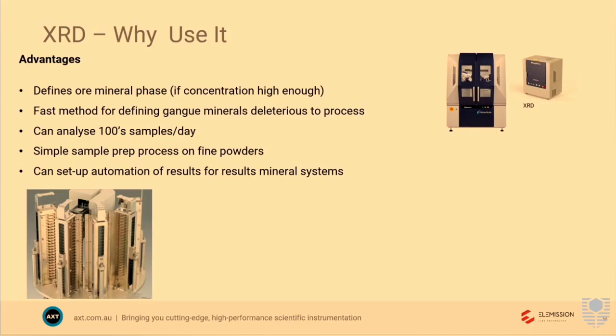All you have to do is pulverise, and then you actually have to micronise a little bit further to try and get everything down to hopefully less than 40 microns. The ideal particle size for XRD is meant to be 5 microns, but if you grind everything to 5 microns, you end up with so many amorphous phases that you can't analyse them. So industry typically will pulverise something down to less than 40 microns, and a researcher will be in shock horror, you've got to be less than 10, but industry just doesn't go, they want to analyse hundreds of samples, and so less than 40 microns tends to give them what they want. And you can set up the automation of results for minerals analysis.